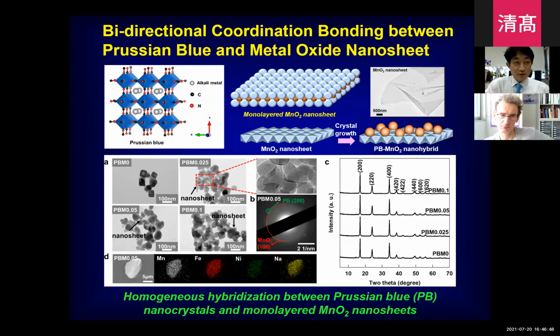Also, we use the exfoliated manganese oxide nanosheet as a substrate to immobilize many kinds of nanostructured material and inorganic species. This is one example of the anchoring of Prussian blue nanocrystal on the surface of manganese oxide. I want to emphasize that a lot of the surface-exposed oxygen can act as a linker ligand to connect to the metal ion in the Prussian blue lattice. Also, manganese ion is somewhat exposed to the surface, so there is another possibility of linkage between the cyanide ligand and the metal ion in the manganese oxide nanosheet.